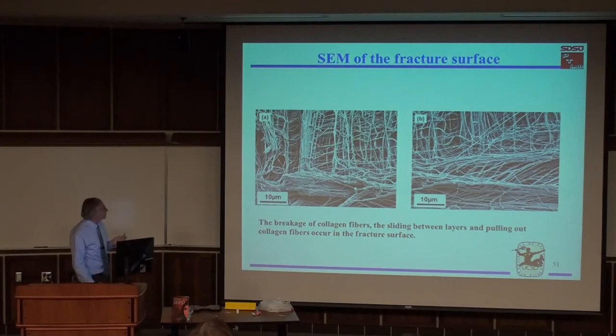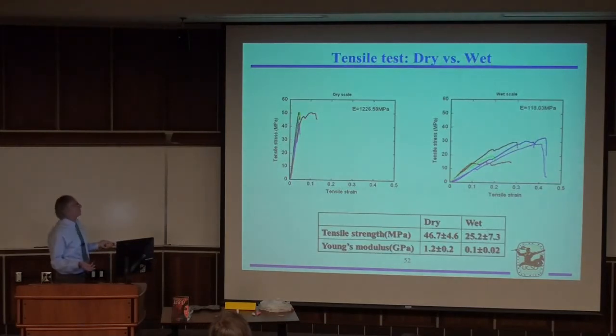Now I'm going to show how hydration is so important. These are the wet scales. These are the dry scales. The dry scales have a stress of about 50 megapascals. The wet scales about 20 to 30. Now if you take the area here, it is higher than the area here, so the toughness is higher here. Now they undergo what's called graceful failure.